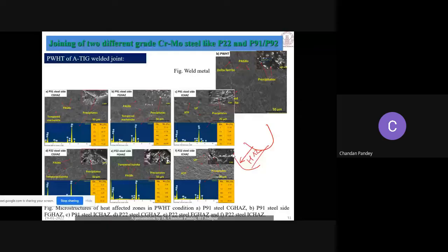So on one side we are getting the benefit, but on the second side, due to the diffusion of carbon, we get the formation of a carbon depleted and carbon enriched zone. So that will create a problem. On one side you are getting the benefit, and on the other side you are getting a loss of homogeneity due to the diffusion of the carbon element. Now, this is about the EPMA study that shows the diffusion of the element and the formation of the carbon enriched and carbon depleted zone. In the carbon enriched zone, we get a higher percentage of carbon in that region and a lower amount of iron.